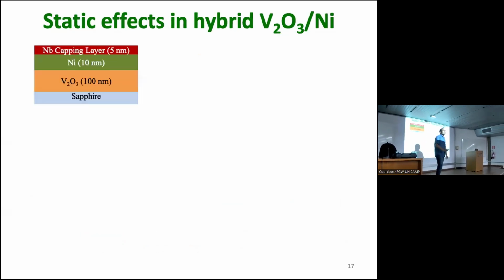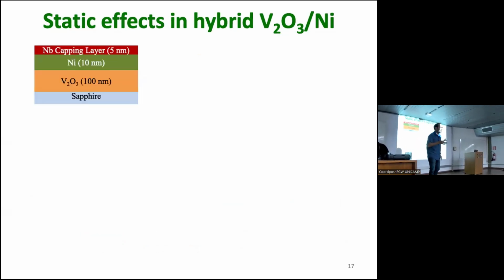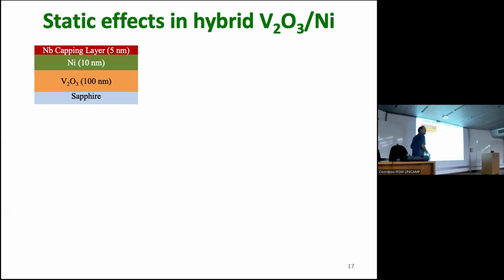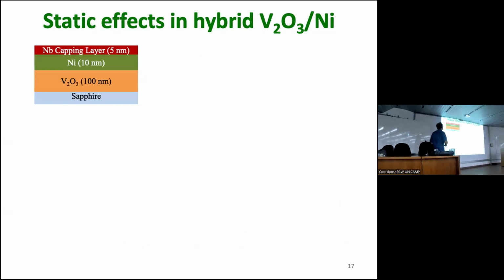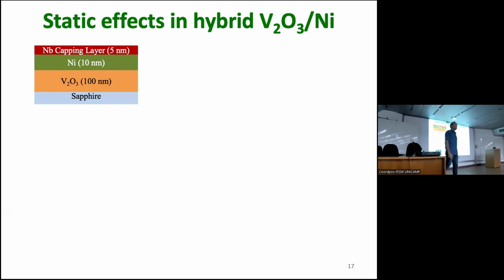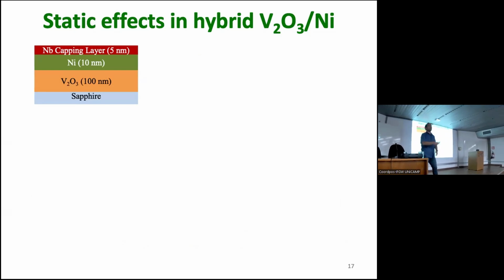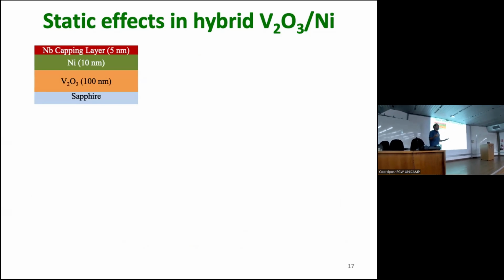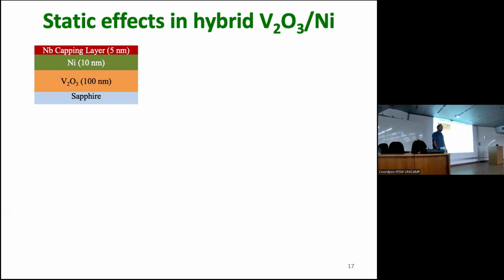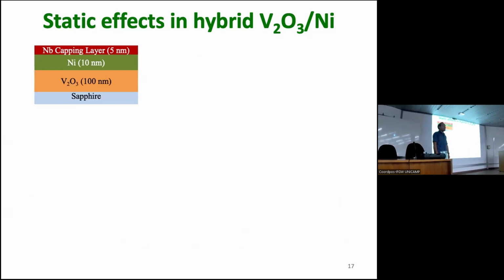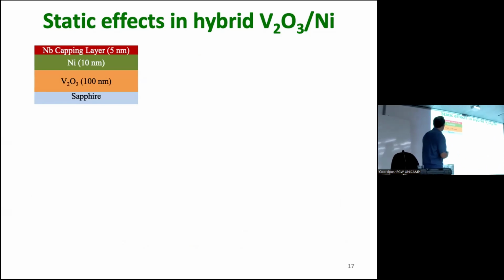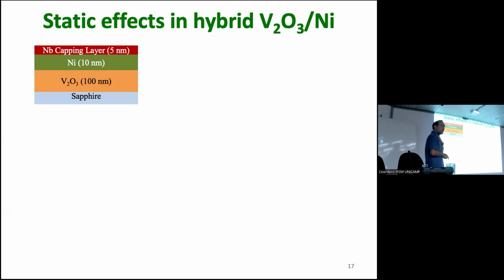And then this is something we wanted to do: go to the interface of the transition and then use it for something interesting. The first thing I came up with was to put vanadium oxide next to anything. And the first thing we decided to do is just put on top of it a metallic ferromagnetic material, something that is very soft, mechanically soft. So then you put nickel. So what is going to happen here, you may ask?